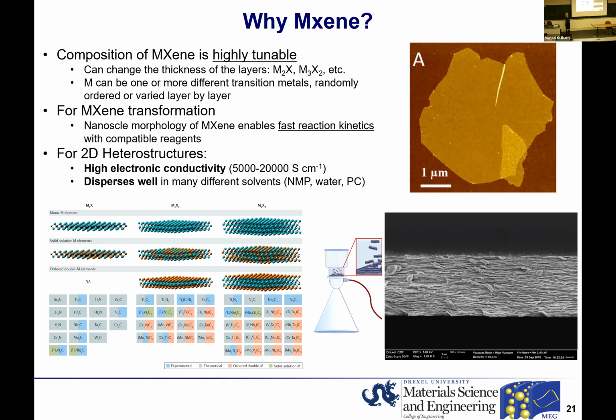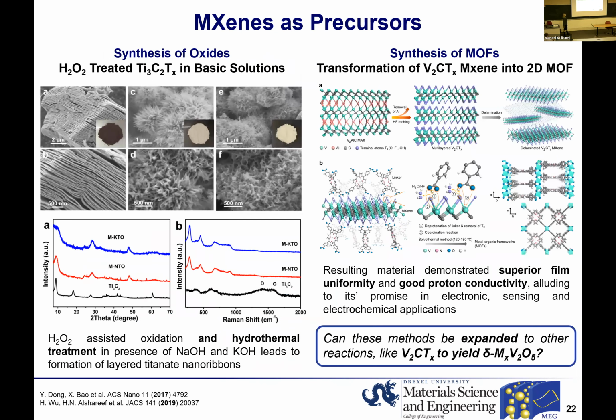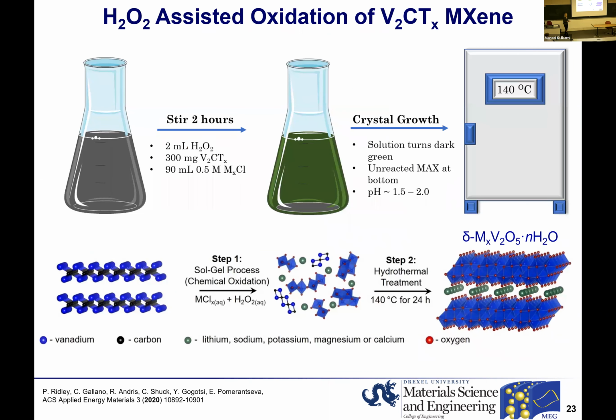We just want to oxidize them. And again, we are not the first ones to do that. For example, there was a report where titanium carbide was used as a precursor to make layered titanium oxides. And also Professor Alshareef showed that vanadium carbide can be integrated with some organic ligands in order to make a metal organic framework. But before us, no one used vanadium carbide to make an oxide material.